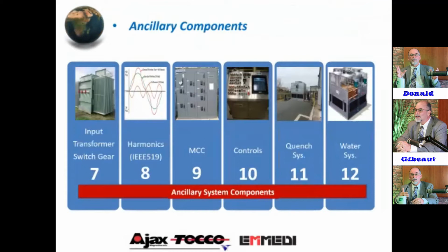Here in the US, we have a specification, IEEE 519. All induction equipment outputs harmonics, and typically we're focused on the 5th, 7th, 11th, and 13th harmonics. We do offer harmonic filters that can bolt onto the power supply. We do a harmonic study, and we can filter out to this IEEE 519 coming out of our power source, which is typically your heaviest source of power in these facilities. All the rest of the equipment, any coating systems, anything else, is typically on another transformer. So you have dedicated transformers for the induction, but we definitely control harmonics, and we do that so that harmonics don't come back into the equipment.